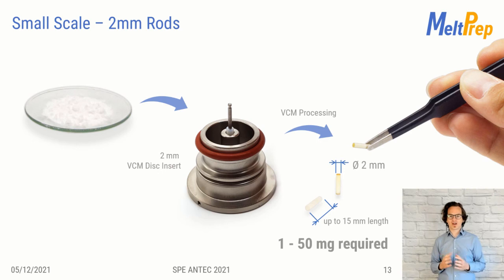One thing that I'm very proud of is the small scale development that we did. I kicked the VCM tool off with a 25 mm disc diameter in 2014. My former colleagues at the RCPE were requesting smaller dimensions for their investigations. We reduced it to 5 mm to make it suitable for DSC and later even to 2 mm diameter. You can use those small dimensions for the screening of implants, for example. 1 to 50 milligrams are sufficient to produce a prototype of a subcutaneous implant.